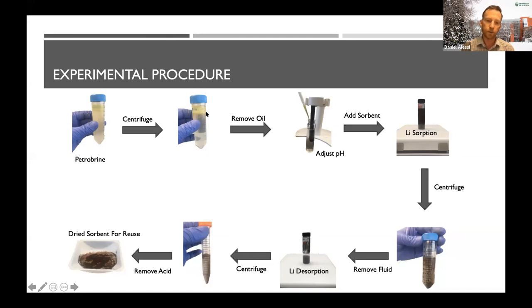At that point, we have the purified, pH-adjusted brine. We add the manganese oxide, a black powder, and that's the step where lithium is drawn from the brine into the sorbent itself, into the ion exchange sites, filling up the sites inside the material. Again, this could take anywhere from 15 minutes to perhaps an hour, depending on the temperature. We do another centrifugation step to remove the fluid. Now it's the lithium-loaded sorbent. What we have on top here is the waste brine. This is the lithium-voided brine. In industry, this would go off for disposal. Here we pour it off into a waste container and we're done with it.